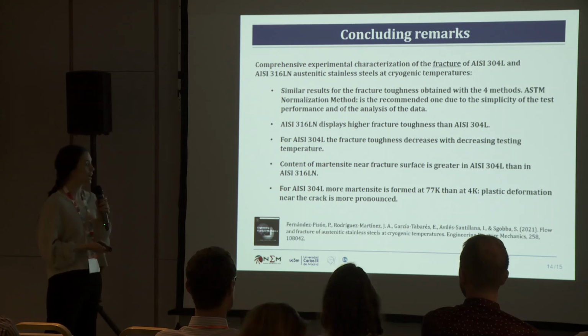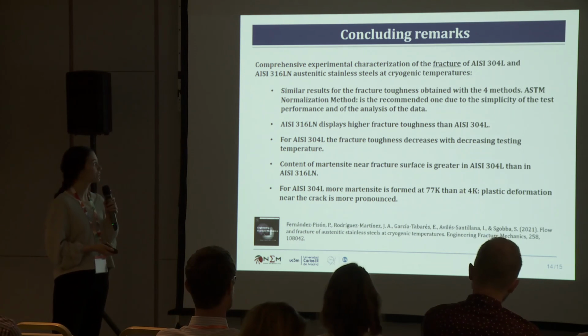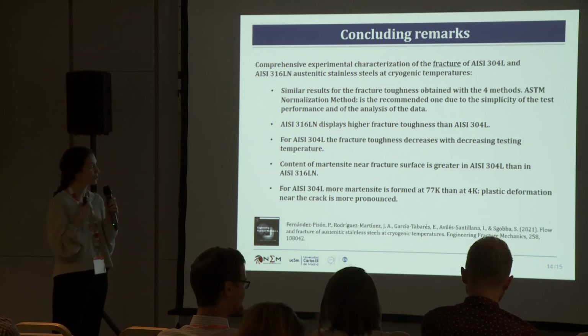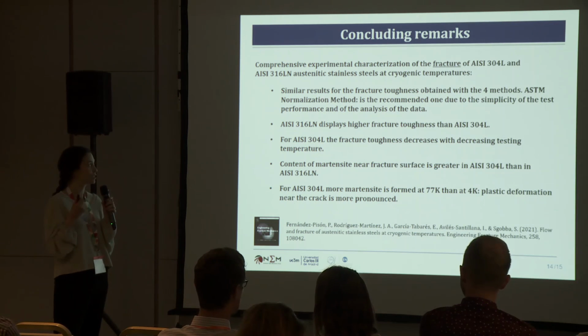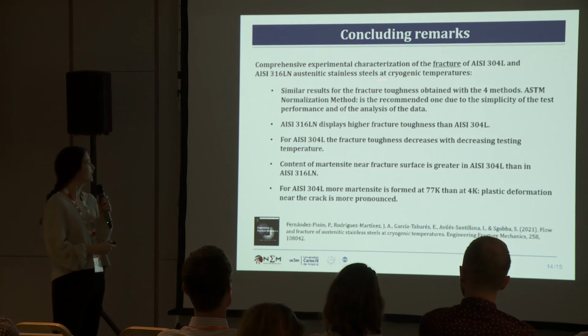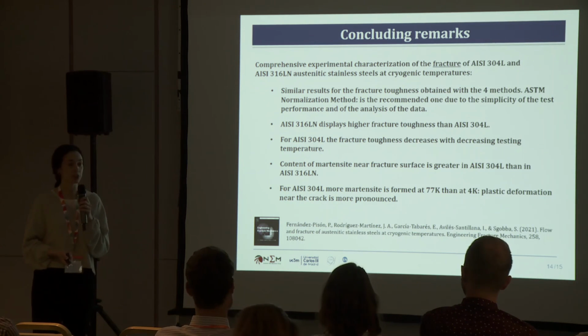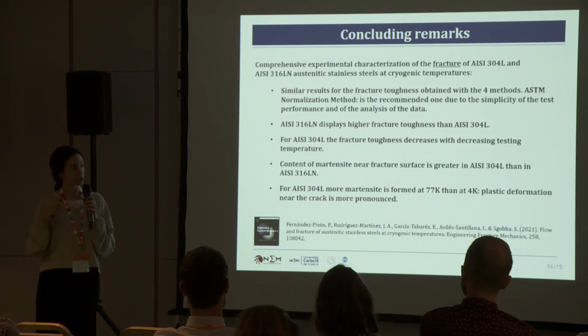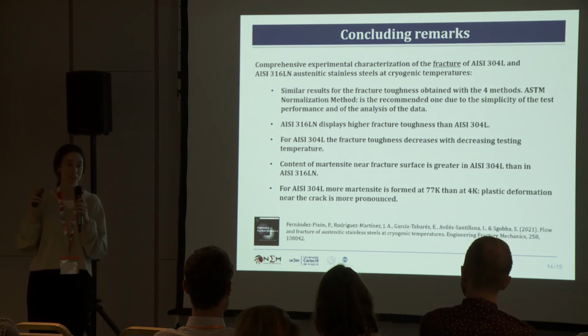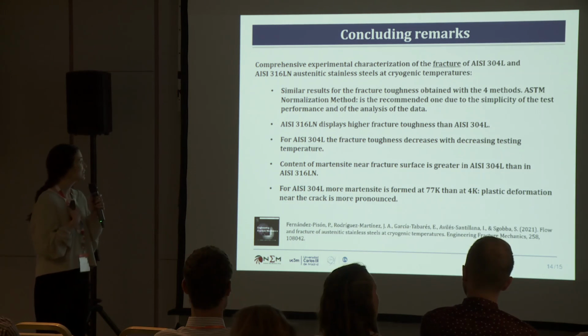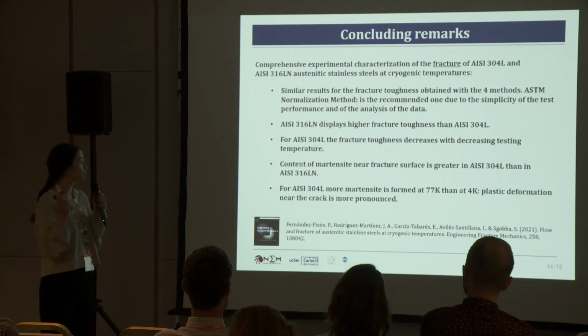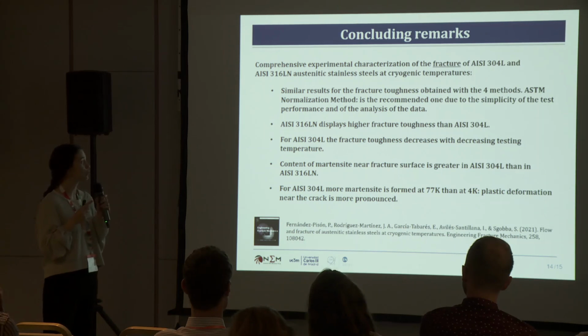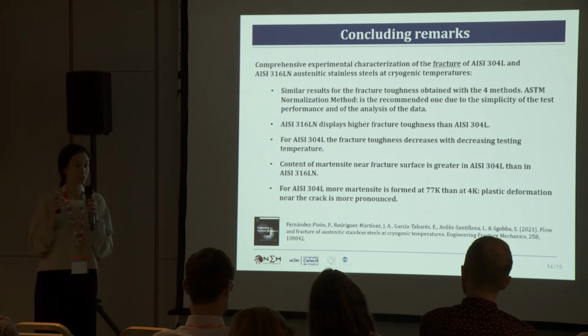The conclusions. I have shown you a quite comprehensive characterization of the fracture toughness of two of the most dominant grades for this kind of application, AISI 304L and AISI 316LN. What we have seen is that when we compare the 4 different methods to calculate the J-R curve, all of them are similar in terms of the points, but we recommended the normalization method. Then if we compare the fracture toughness between the AISI 316LN and the AISI 304L, we have seen that for the 316LN it is higher. And for the AISI 304L, it was higher at 77 than at 4 Kelvin.